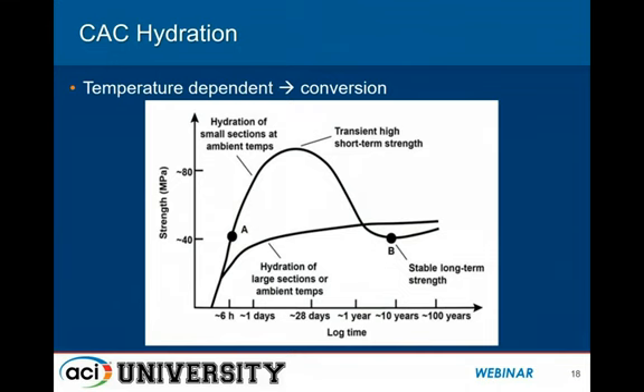Within about 5-6 hours, you see roughly comparable strengths to 28-day strengths of Portland cement systems. So we're up over the 40 MPa or the 3,500 psi range, which is where we want to be in a lot of cases for pavement repair. What we also see is strengths that go much past that in the short time frame. And over time, in this figure, over the period of about 1 year, that transient high strength is then lost over time and becomes stable out past 1 year.